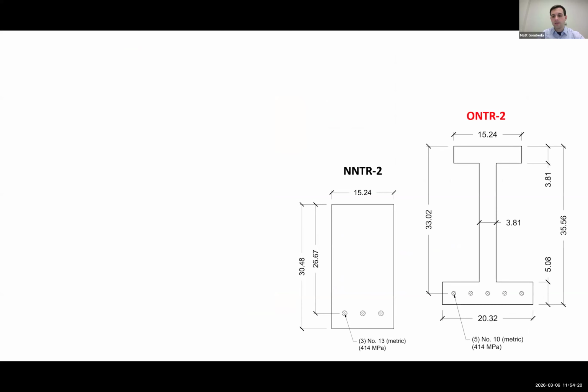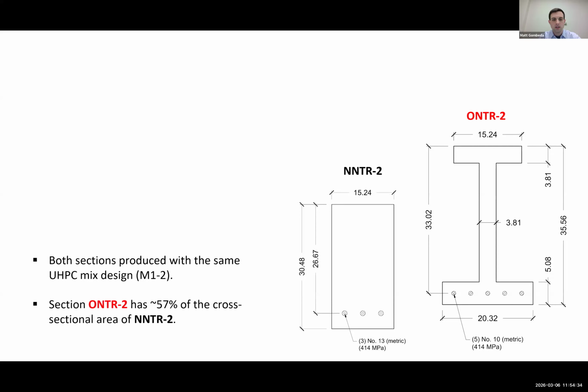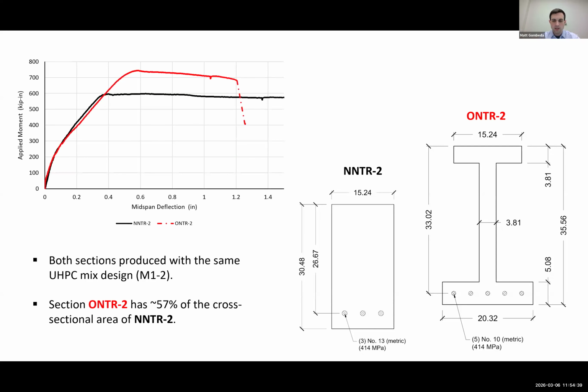Here we then sought to develop an I section, a more efficient use of materials. And it was done really thin. It's like 1.5 inches thick in the web, which you couldn't do with standard concrete. And the idea here was to compete with a structural steel section. The I section is 57% of the cross-sectional area of that rectangular one, but the flexural strength when we ran the computational model gave us about a 20% or so boost in strength.